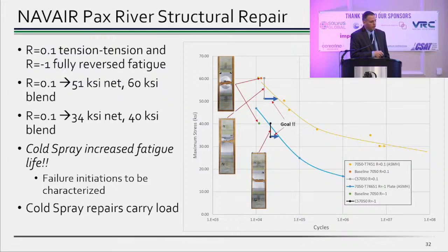And if you look at the improvement we get at both R equal 0.1 and R equal -1, we're seeing an increase in load carrying capacity. Now, we haven't gotten back to the full strength of the material. That would be where these blue arrows are. We would want to push those cycles out to that yellow line or that blue line. But we are getting increased capability over the divoted sample. So if you can allow a blend, then you can repair it with this and not have any further damage to the part.